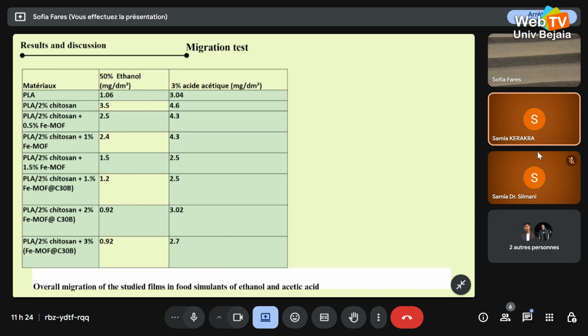The migration test. As we can see in this table, all films show migration values below 10, meeting the EU regulation, and adding 2% chitosan increases the migration due to the hydrophilic nature and OH and NH2 groups, which favor diffusion. And the addition of clay and Fe-MOF reduces migration thanks to their barrier effects, creating tortuous diffusion paths that slow molecule passage. These composites balance biodegradability and barrier safety, making them suitable for food packaging application.